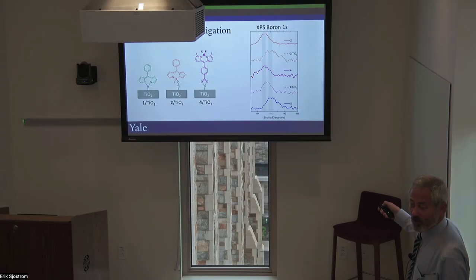So it tells us there's a change in the boron coordination. On the other hand, this carboxylic acid derivative has a similar binding energy free in solution and doesn't shift very much on the surface, which is telling us it's not binding through the boron end, but through the carboxylic end, which we expected.